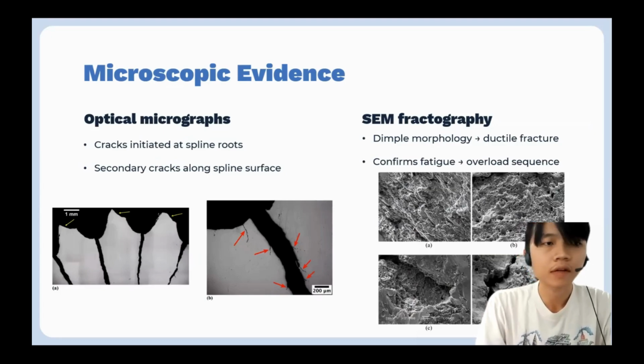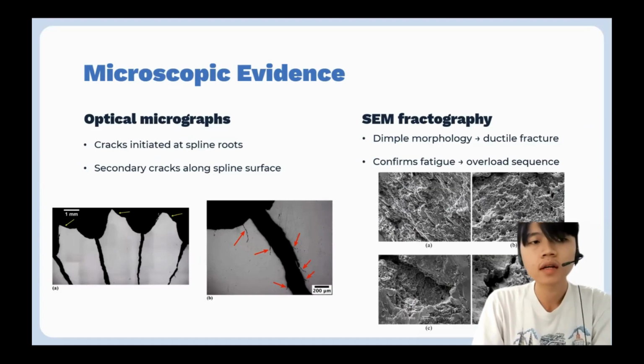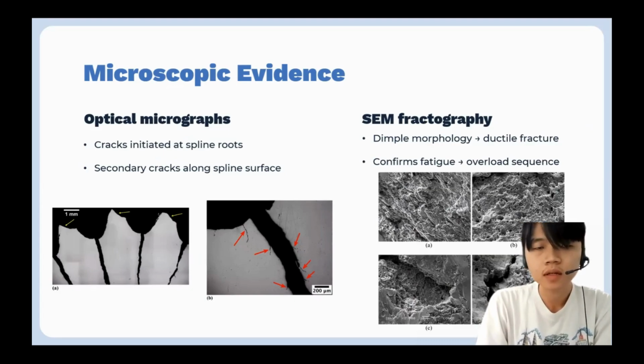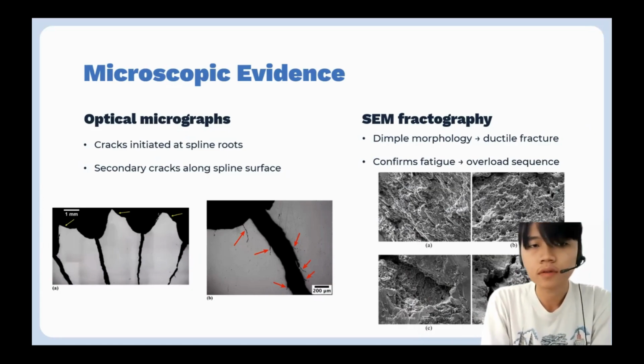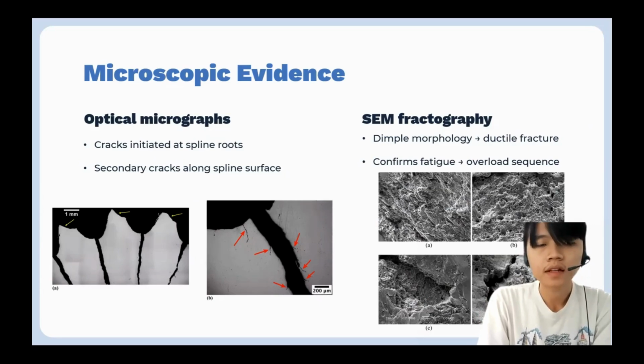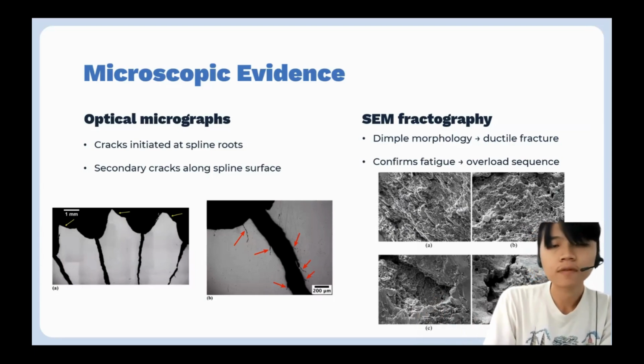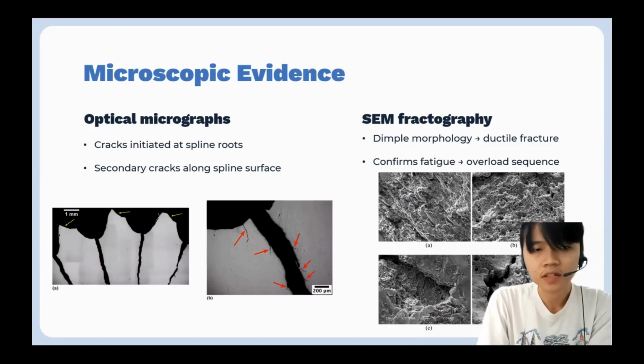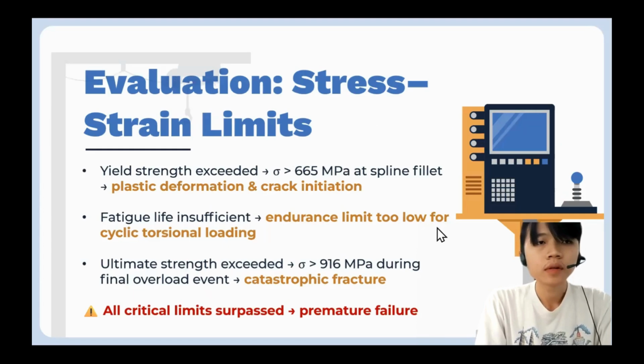We have some microscopic evidence, where the analysis shows a failure sequence that confirms our analysis. The optical micrographs revealed multiple cracks originating from the spline roots, where the stress concentration is highest, and secondary cracks are also observed along the spline surface. At higher magnification, SEM fractography gives us a dimple morphology, which is a mark of ductile overload. Together, these microscopic features confirm that the shaft first failed by fatigue, crack initiation and propagation, and then fractured completely by ductile overload.